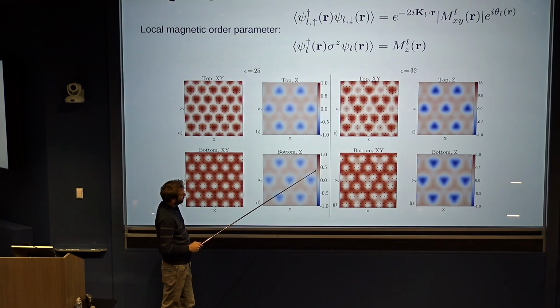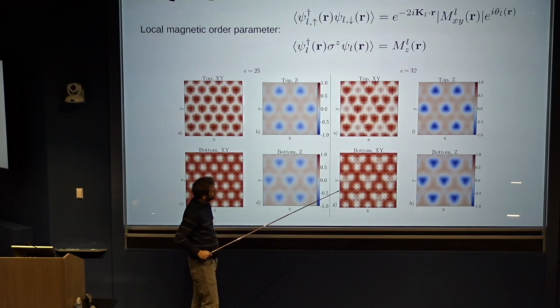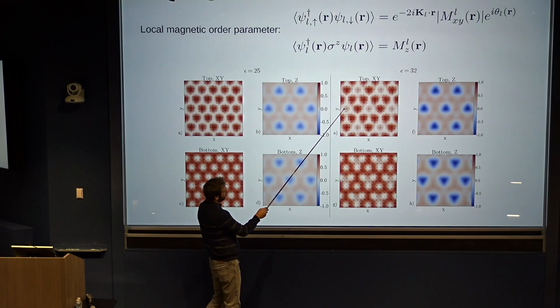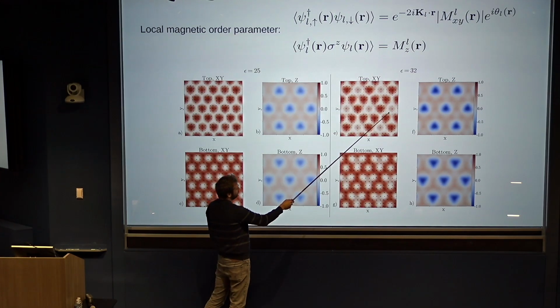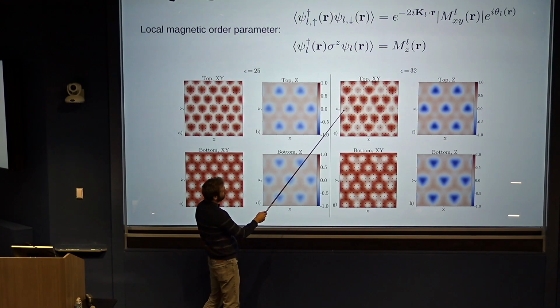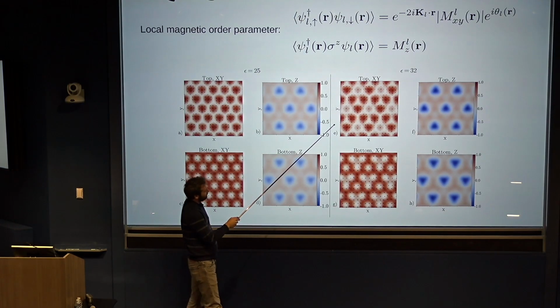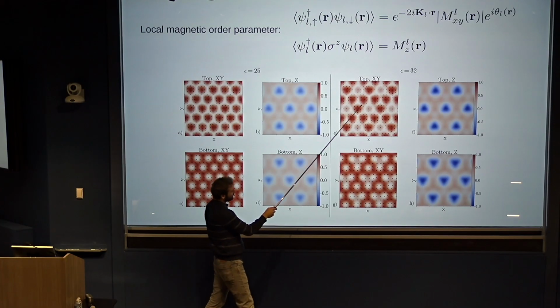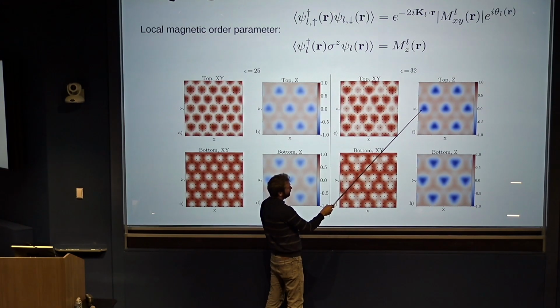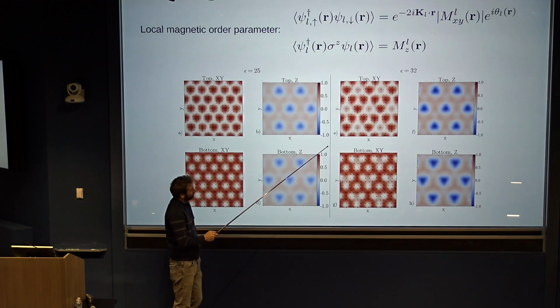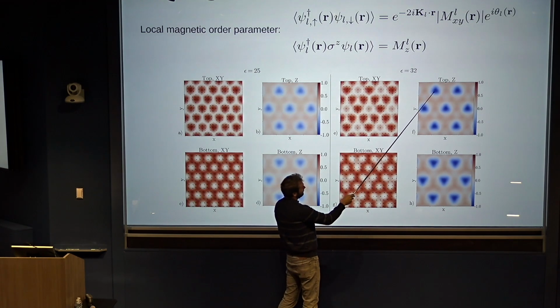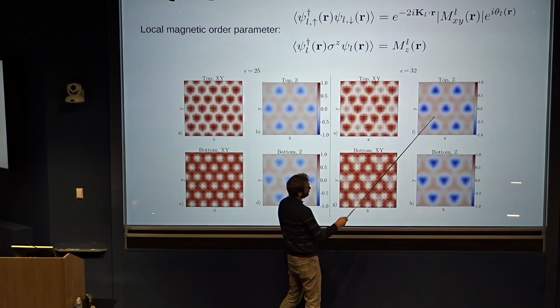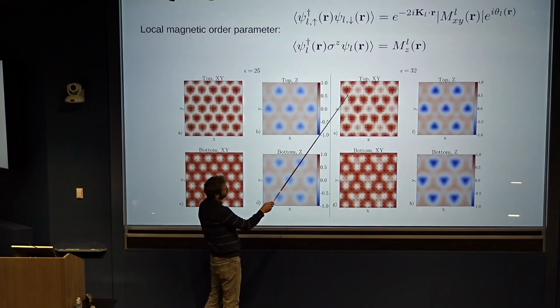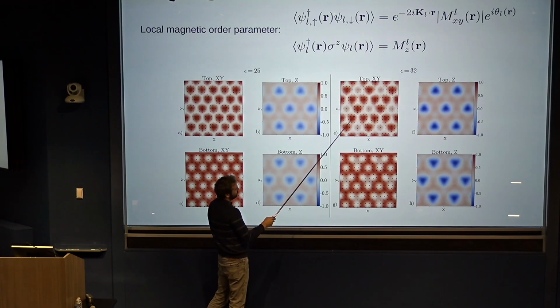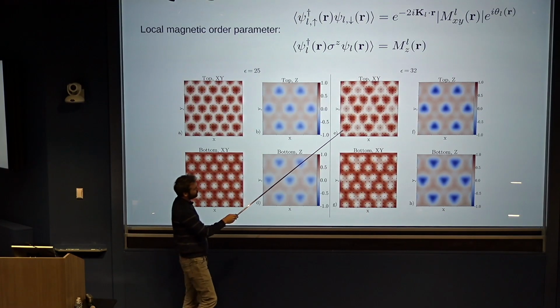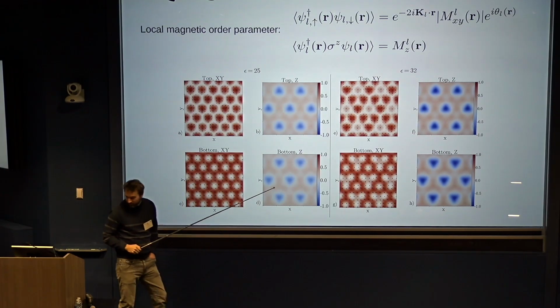And what you see here is a more complex pattern. It has a larger spatial unit cell. What's happening is that in 1/4 of the Moiré unit cells, the magnitude of the in-plane magnetic moment decreases a lot, and it's replaced by a significant out-of-plane moment. So we have this triangular lattice of out-of-plane ferromagnetism, which is interwoven with the remaining Kagome lattice, where the moments still form this 120-degree order, but now on this Kagome lattice.